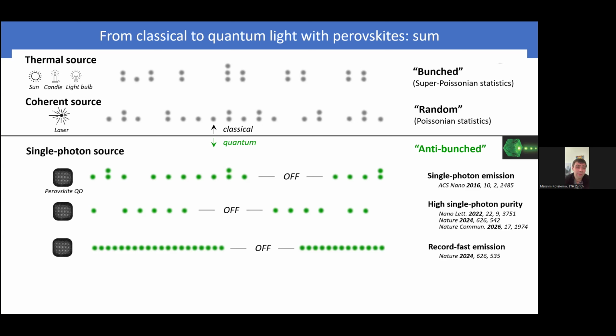But still, we do produce some, and we start to publish very luminescent, very bright perovskite layers, which are nanocrystalline. They're not continuous layers, but they are like islands. And depending on the substrate, we actually do in our group thin film evaporation of the perovskites into such islands, and they are also very bright emitters.